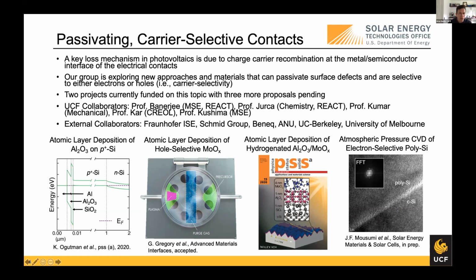So we published that. We found that worked pretty effectively, although when you put metal directly onto that aluminum oxide layer, you can only use that really as an effective back contact because you're covering the whole surface with metal. So we're also looking at layers that you can put on the front to replace the metal that can be hole selective. So we just published something recently in Advanced Materials Interfaces where we're looking at a high throughput, what's called spatial atomic layer deposition of a material called molybdenum oxide that essentially supplies effective band bending to prevent electrons from moving to the contact. So we're pretty excited about those developments.